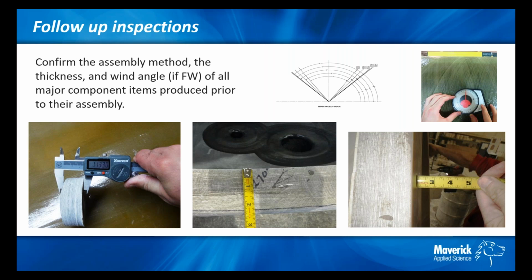If you inspect the laminate and find that it meets the thickness requirements shown in the drawings, you might be satisfied to move on and let the fabricator buy you an early lunch. But if you notice that the laminate type they built was a contact molded construction when the design drawing showed you a filament wound laminate was required, then your thickness measurement is incorrect for that laminate type.